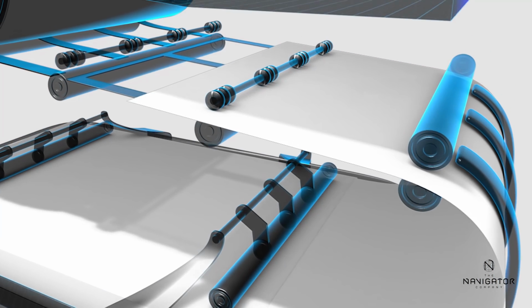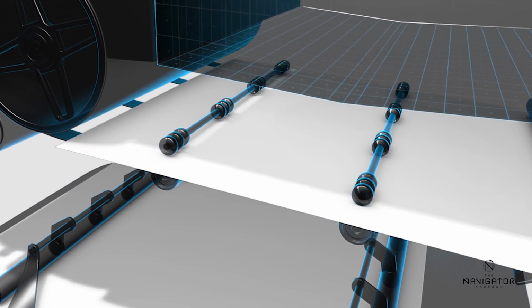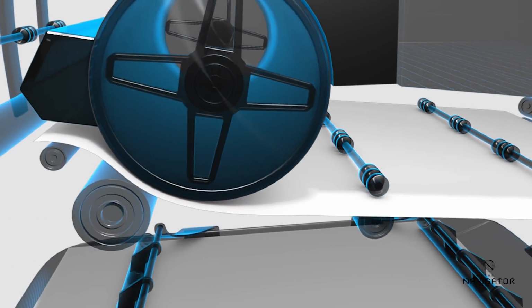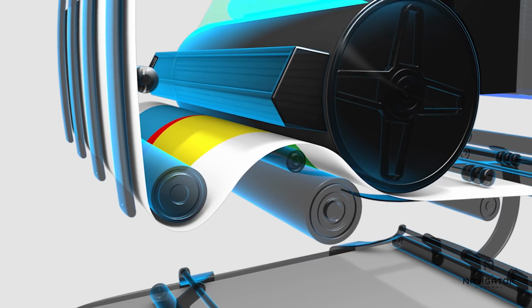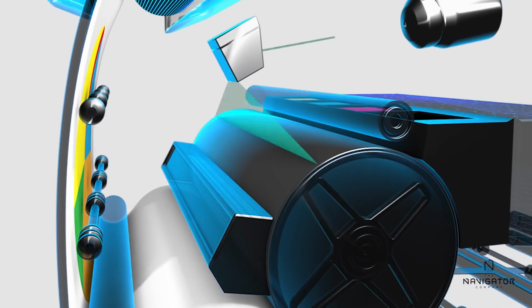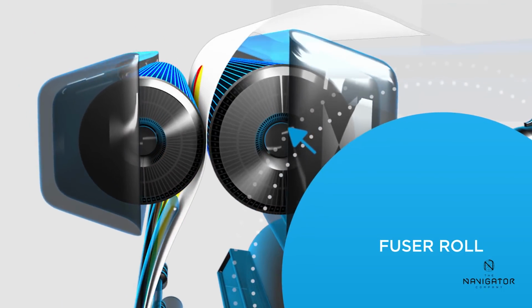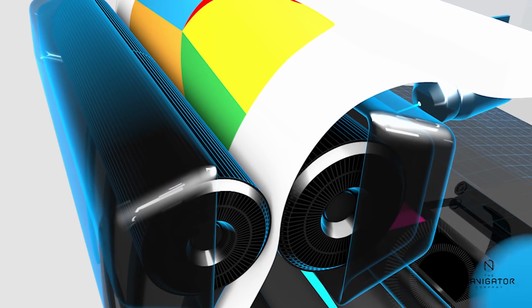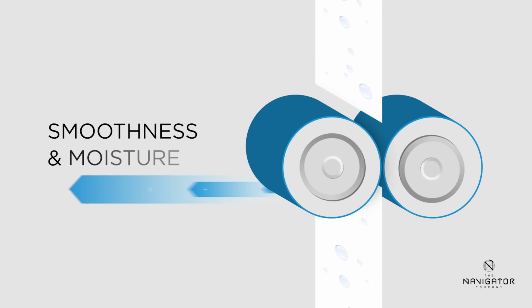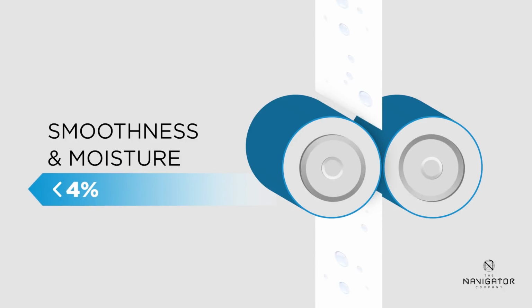To fix the toner, the sheet is heated under pressure in the fuser roll using high temperatures, 180 degrees Celsius. If the paper moisture is excessive, it will evaporate in the fusing phase, leading to poor toner adhesion and curl issues. During this step, the most important paper characteristics are smoothness and moisture level, below 4%.